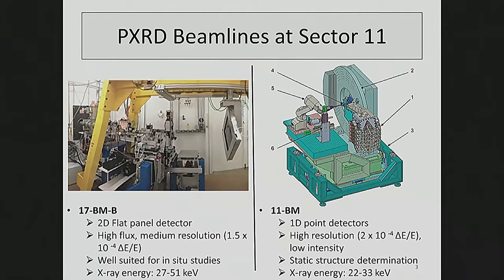So essentially, 17 BM uses a 2D panel detector, so it can collect data very, very fast, and it has a high flux of X-rays. But because of that, it has medium resolution, but it's still orders of magnitude better than your home powder diffractometer. Whereas 11 BM has a 1D point detector, so what's happening here is your X-rays are diffracting off your material, and then they go through an analyzer crystal, so you're actually collecting that 1D diffraction pattern, but it takes a really long time, like 6 to 12 hours. So because of that, 17 BM is extremely good for in situ studies, whereas 11 BM is really good for structural studies at fixed temperatures.